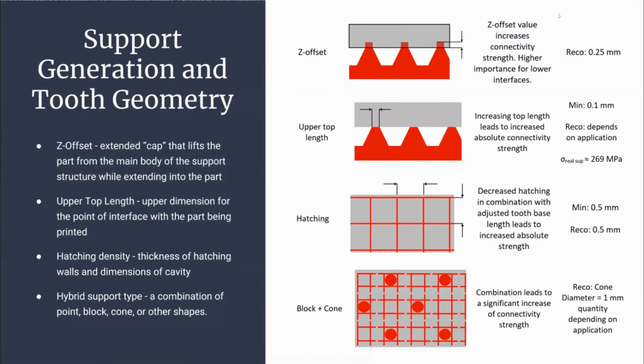So moving from our CAD geometry to our support generation and preparation for print, this goes back to the paper we were talking about by Lindicki. We were looking at basically 4 major factors that go into determining the support structure. This was the Z offset, which is like a little cap that sits on the top of the support structure that separates the part itself being printed from the support structure that connects it to the build plate. The top length of that support, this second illustration from the top; the hatching density, that is, how dense the support structure is going to be; and then whether or not we're using a hybrid support structure, that is, a variation between a block, which is just a straight line or rectangular shape, and a cone, which is obviously a conical shape, and what strength considerations would go into using both of those.